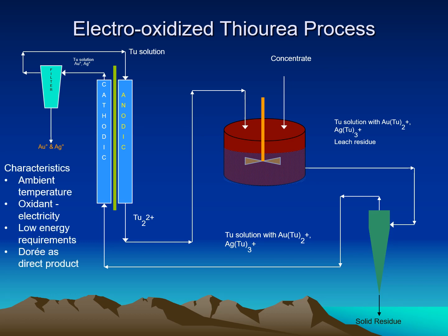anodic compartment. The characteristics of this process are ambient temperature. The oxidant is actually electricity, and also the reducing agent in the electrochemical reactor. It has very low energy requirements, and the product of the process is gold, silver, doré. The challenges for this process are it's not adequate for acid-consuming ores. That's why we use concentrates for this process. And also, base metals can decrease the yield, especially if there's a large amount of soluble copper. However, we can correct this problem by additives that depress the leaching of copper, especially.